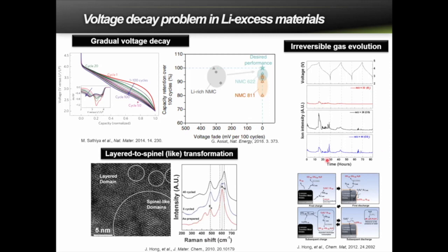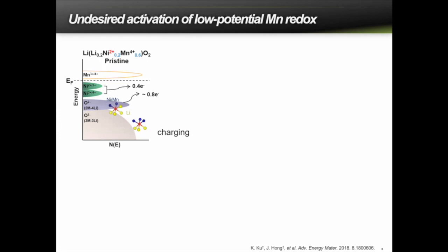Regarding the voltage decay problem, our group has previously reported that it is correlated with the local phase transition from this layered structure to the disordered or spinel-like structure like this. And we suspected that it might cause an unwanted change in the redox reaction. So, inspired by this previous finding, we hypothesized that the decay of the voltage is partly induced by the structural transition and the activation of low potential redox reactions such as manganese. Taking one representative lithium excess material, Li1.2Ni0.2Mn0.6O2, which has about 20% of lithium occupying the transition metal layer, the anion redox reaction is supposed to be possible. We envision that the redox reaction is going to take place like this.